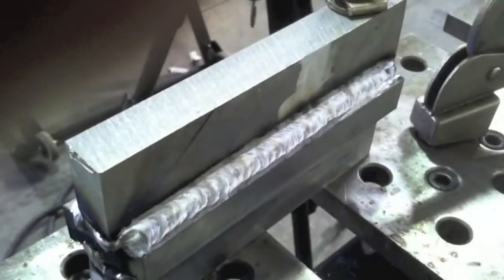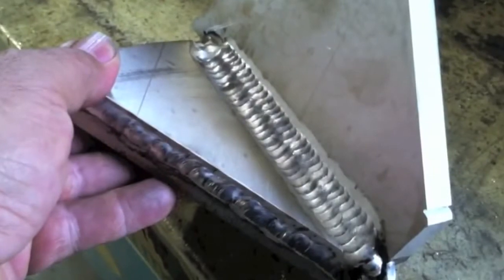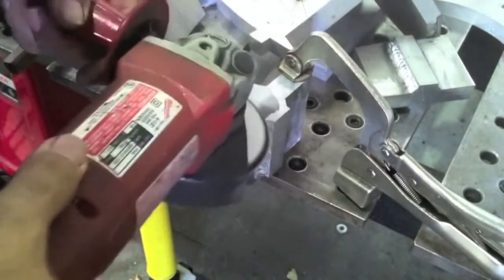All right, before I welded thick aluminum, I got a thick aluminum fixture to do. I wanted to set the machine settings and verify that everything was going to be cool. Not too much spatter, not too much soot, but adequate penetration. So I did quite a few little welds on 3/4 inch aluminum plate. Did some vertical uphill in case I had to, and then also some double pass, little weave second pass vertical uphill. And then sliced and diced that too to check for penetration.